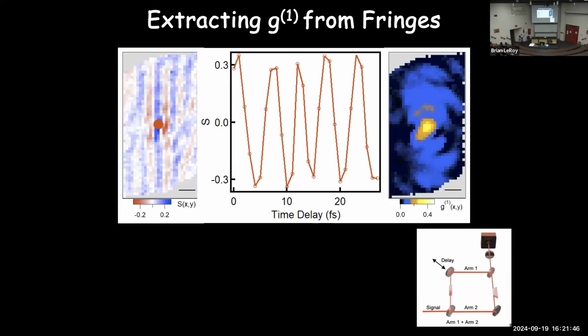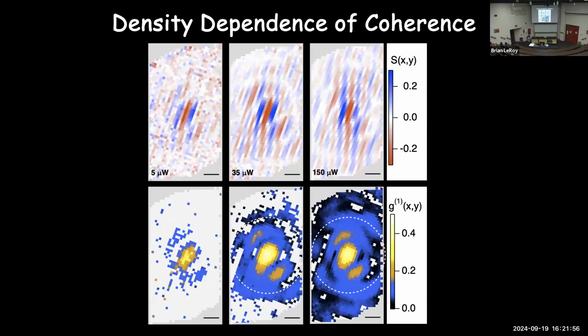So this is showing basically there's coherence everywhere. I have this blue region. There is coherence. Where there's black, there's no coherence. I do that as a function of the density of these particles. I control the density by how much power I put in, by how much laser power I use for excitation. At low laser power, there's only coherence right at the center. That's basically the same point overlapping with itself. So of course, it's going to be kind of self-coherent. As I increase the power, that coherence grows and gets eventually over the entire area of the sample.